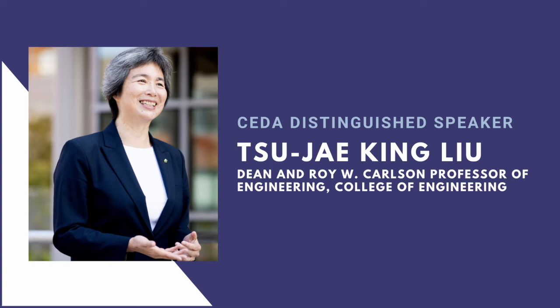I forgot to point out, it was hopefully obvious, we don't rely on the switching speed of the mechanical beam to actually perform the function, like the lookup function. That's why the readout delay can be low, because the contact resistance can be low compared to a CMOS circuit. But if you really want to do mechanical computing or oscillators, it will be limited by the resonant frequency. And I'd say safely gigahertz, you can assume, is relatively straightforward to achieve with modern process technology.